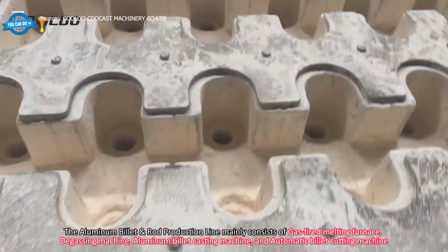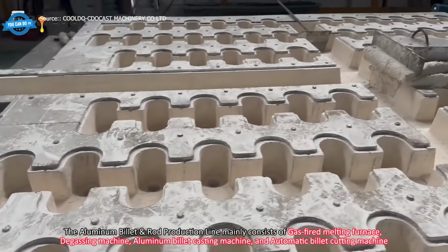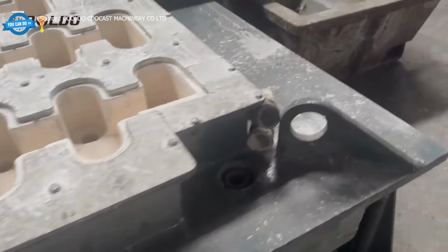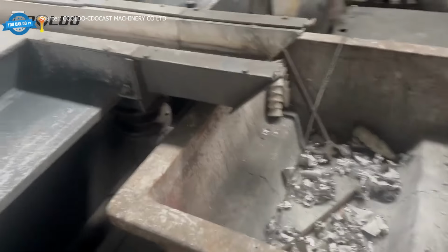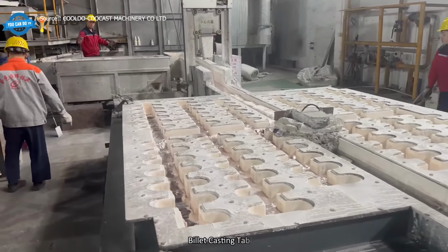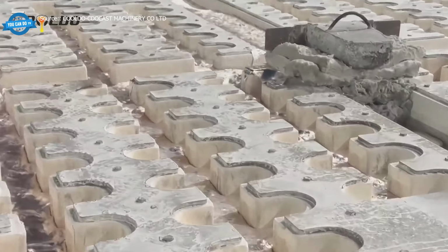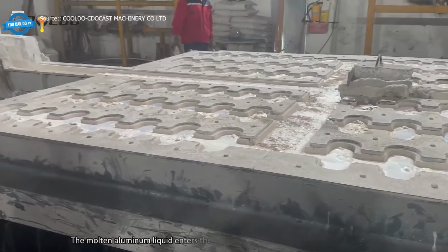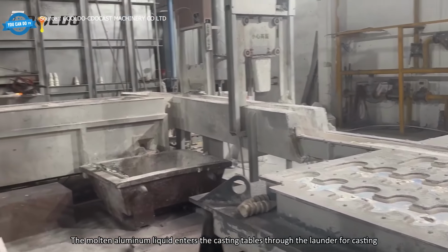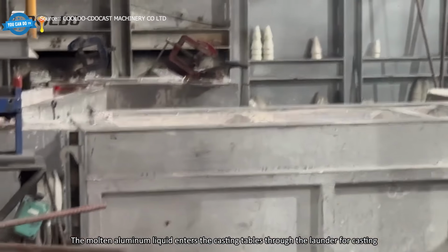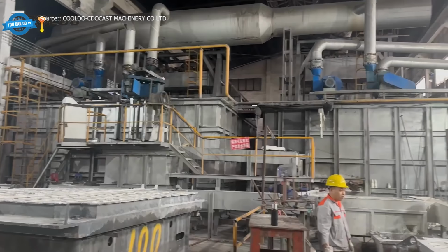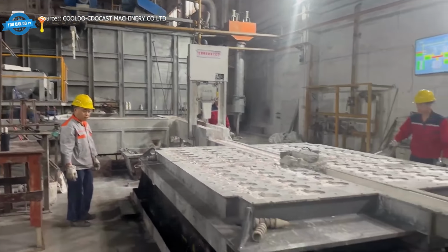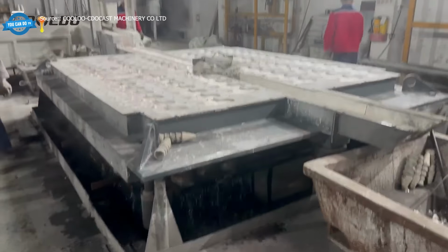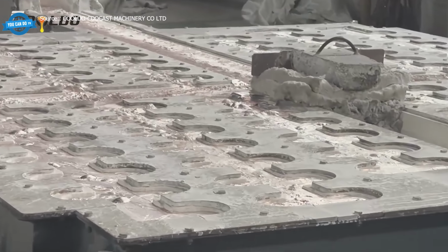The billet casting line is a chain of specialized machines that operate as one continuous system. Gas-fired melting furnaces bring the aluminum up to pouring temperature. A degassing machine strips dissolved hydrogen out of the melt. Hydrogen porosity is one of the classic villains of aluminum casting, and if you skip degassing, you will find hydrogen bubbles trapped in every billet you make.